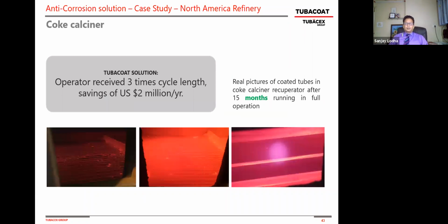So what you see here is, again, when you look through a furnace window, middle picture, what you see is a unique, consistent temperature profile across all the tubes. You don't see any tubes broken, melted, or plugged. Full heat transfer, full throughput capacity they're utilizing, and they got close to 2 years, 3 times the cycle length they would have otherwise. Savings of close to $2 million for this customer, which is a West Coast big refiner in the US. And again, they were very happy with this particular outcome. And we continue to work with them now as a regular supplier and multiple other applications.